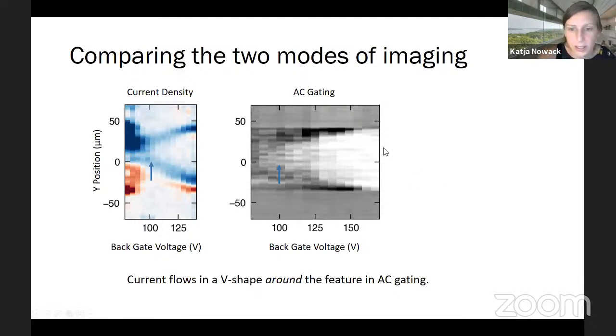And so the way we interpret this wedge that defines this V shape is really that it's the valence band actually coming into the device in a non-uniform fashion. That's the part of the device that develops a finite sigma XX, and so that is the area that the current tries to avoid, and that's also the area where sigma XY locally goes down, and so we expect a much smaller signal in the AC gating.